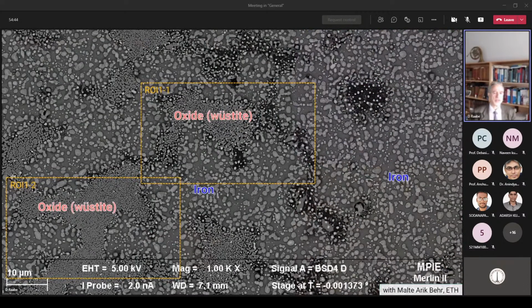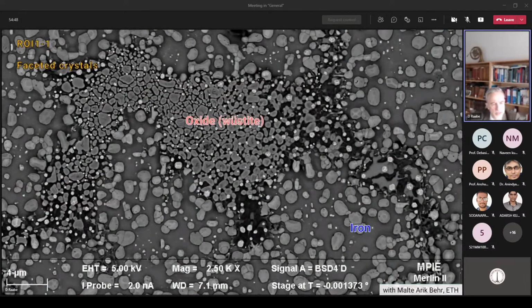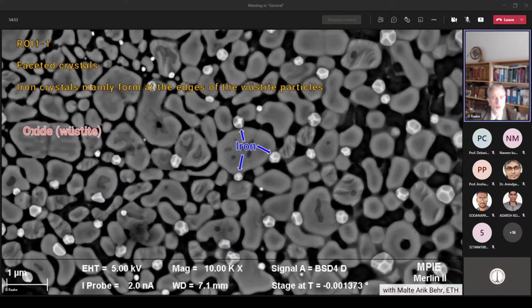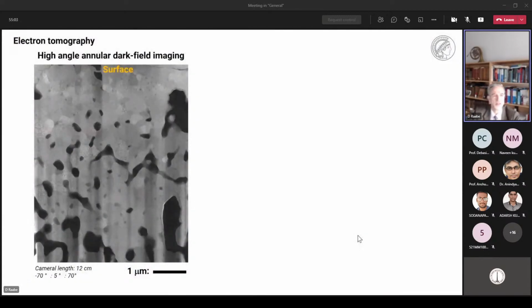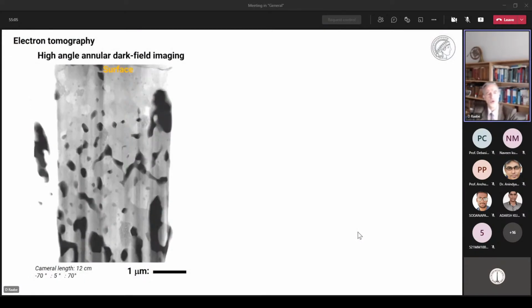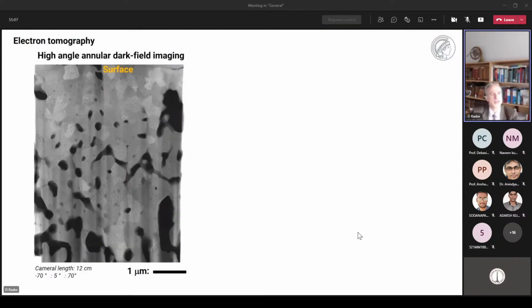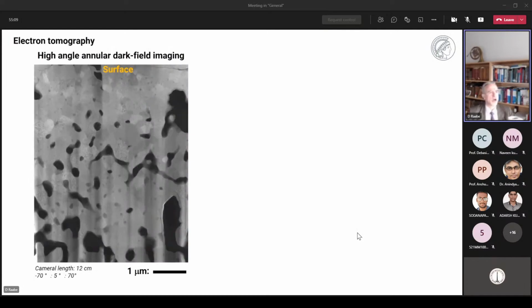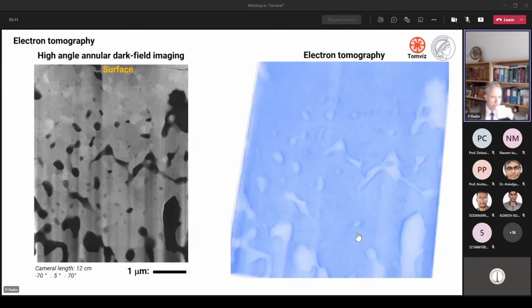And we do the same thing here also together with colleagues at ETH, with Malte Arik Beer in his PhD, where we study two-dimensional wüstite films, expose them in the environmental electron microscope to hydrogen, and see how certain iron nuclei are forming, what their Wulff shapes are, where you have plane match, and so on. And then we go into high resolution. There's another example here where we study this by high-angle annular dark field imaging.